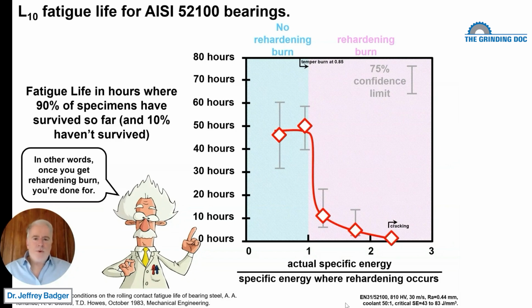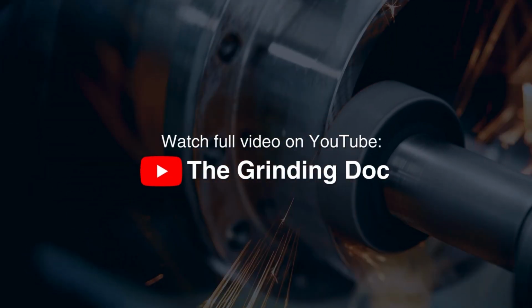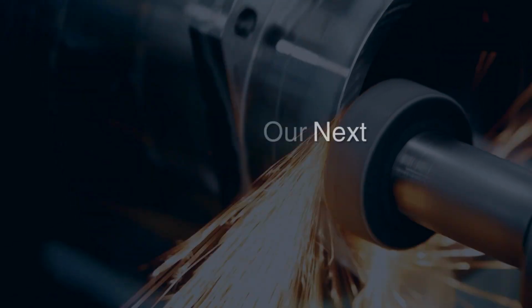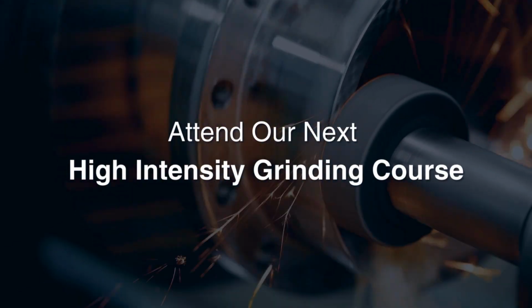But the moral of the story is, if you grind your material abusively and get a little bit of over-tempering of the material, it's probably not going to affect your fatigue life that much. It's not good. You have a softer material, but it's not good. If you grind abusively and you get some residual tensile stresses, well, that's not good either, because that's going to weaken your material, but it's not going to affect your fatigue life drastically. But as soon as you get into the realm of rehardening burn, that's when your fatigue life goes down a lot.